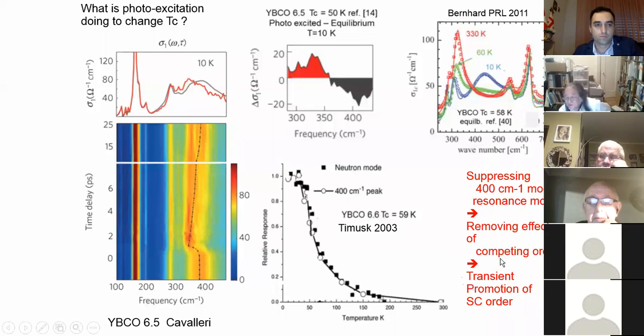And the laser is removing the effect of this competing order, and so removing this 400 Kaiser response. And this means that the laser is removing the magnetic order tendency, and that is promoting, because it's killing the competitor, the superconducting order. Okay, so this is my way of interpreting why transient superconductivity can happen, because I think the laser is killing the tendency of competing order.